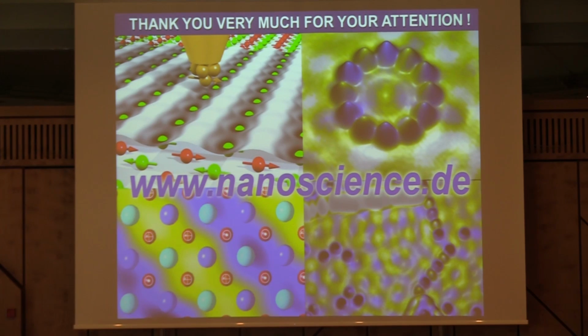And this is a way, for instance, to image objects like skyrmions, which are highly non-collinear objects, with non-magnetic tips. So everybody can look at skyrmions even down to the single-digit nanometer length scale by just a conventional STM. However, you cannot prove the chiral nature of the objects. For this, you really have to do spin-polarized STM.